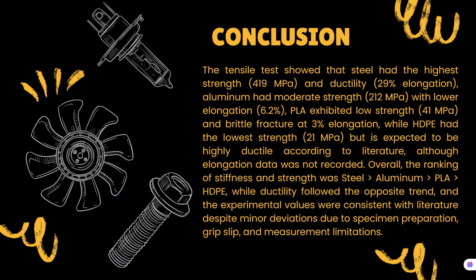So, the conclusion: the tensile test shows that steel has the highest strength at 419 megapascal and a ductility of 29% elongation, while aluminum has moderate strength at 212 megapascal with lower elongation. And then we can rank all of these by strength and stiffness. The first is steel, second is aluminum, third is PLA, and fourth is HDPE. Ductility followed the opposite trend, and the experimental values were consistent with the literature despite minor deviations due to specimen preparation, grip slip, and measurement limitations. Thank you.